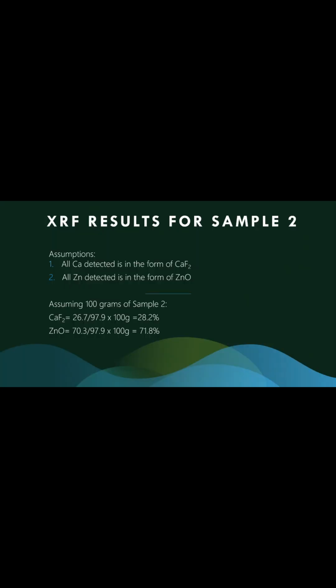Looking at the XRF results for sample 2, we found that there was 26.7% of calcium and 70.3% of zinc. We will be assuming that all calcium detected is in the form of calcium fluoride and all zinc detected is in the form of zinc oxide. This is assumed because fluorine and oxygen are lightweight elements and could not be detected by XRF. So assuming that there is 100 grams of sample 2, we can calculate that there is 28.2% of calcium fluoride and 71.8% of zinc oxide.